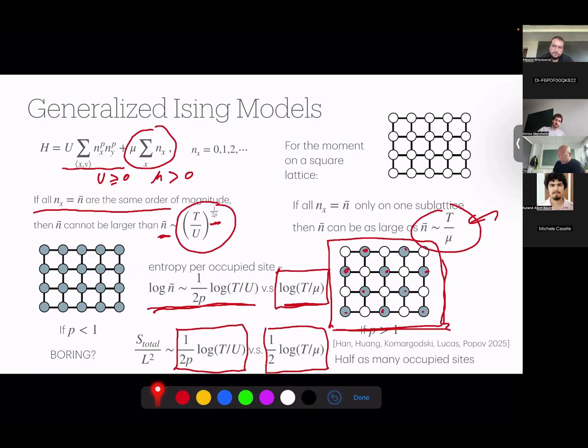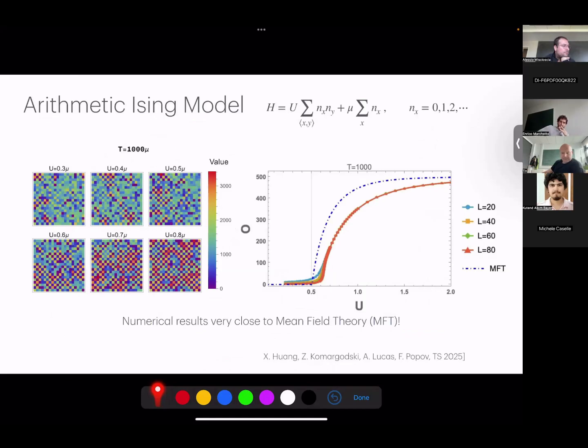And when p is equal to 1, it's more subtle, because the entropies of both the ordered and the disordered phase scale the same with temperature. But as you can see here, there are different parameters u and mu. Which one wins when p is equal to 1 depends on u and mu. And it's very easy to see that if u is much larger than mu, order wins. To check that, we did lattice simulations of this model.